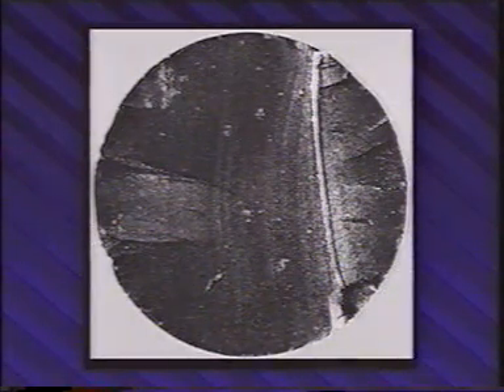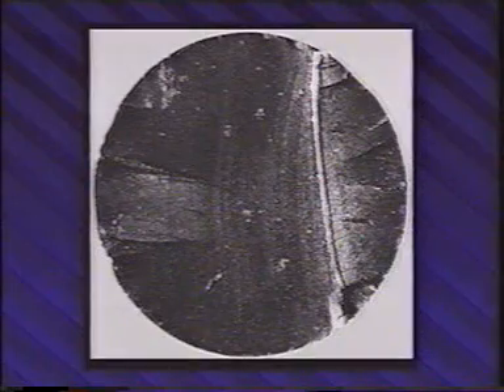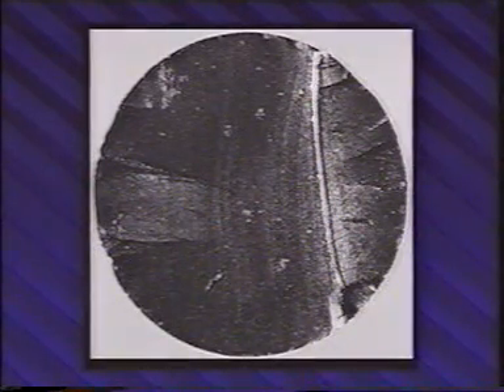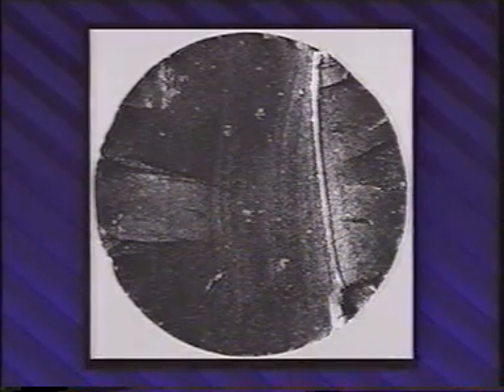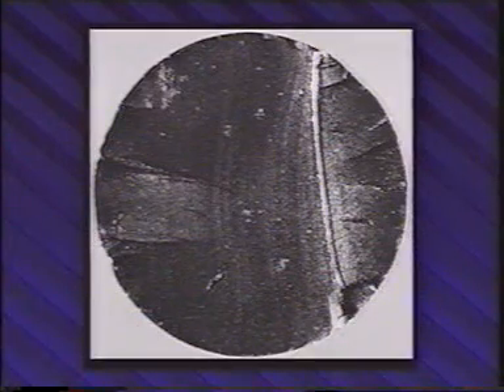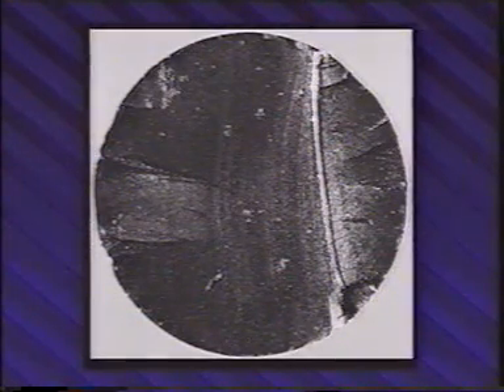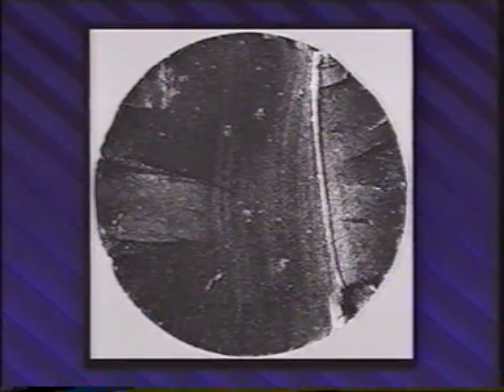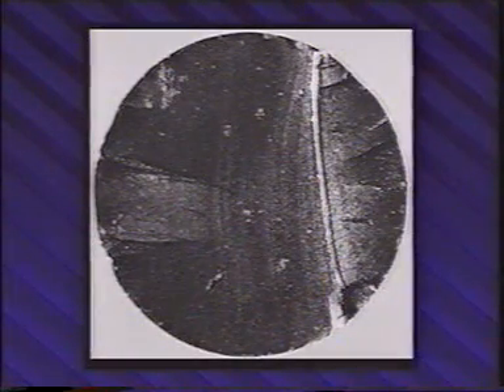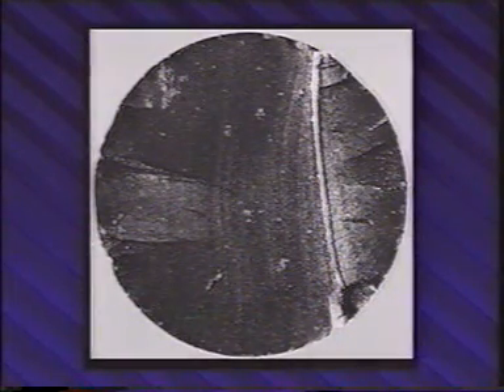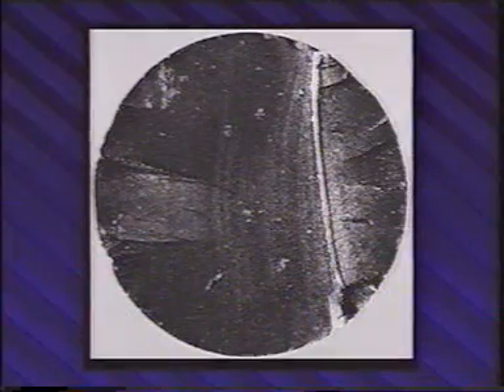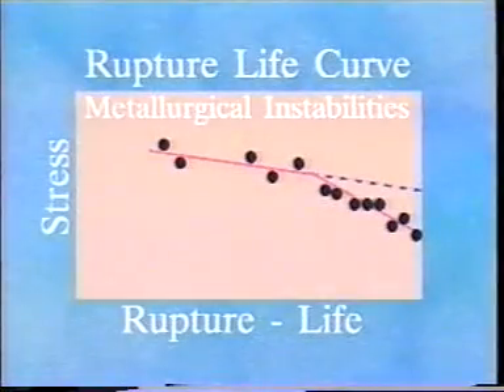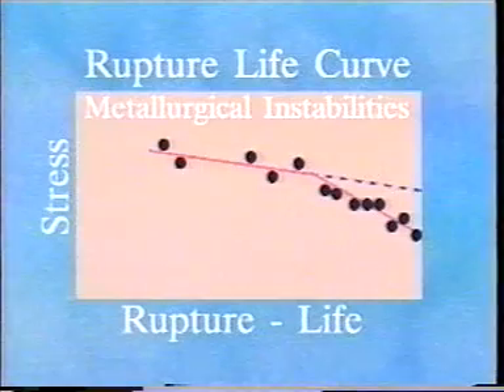Typically, fracture surfaces of components cracked in stress rupture are irregular and discontinuous. In contrast, thermal fatigue fractures exhibit relatively flat, continuous surfaces. During service, the metallurgical structure of a part may be changed by the action of stress, time, temperature, and environment. The result is a change of strength. These changes are called metallurgical instabilities. The instabilities are indicated on the rupture life curve by a sharp change of slope.